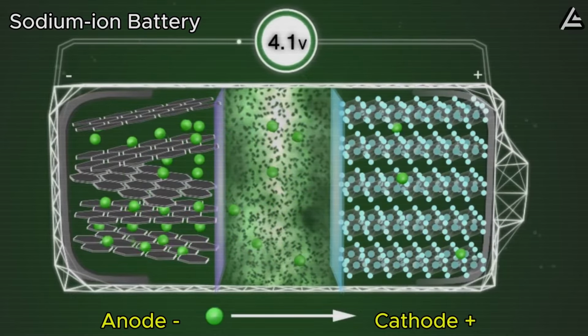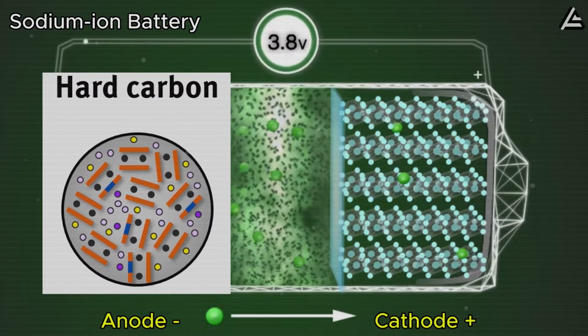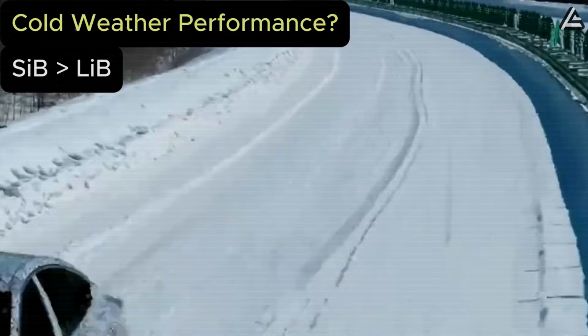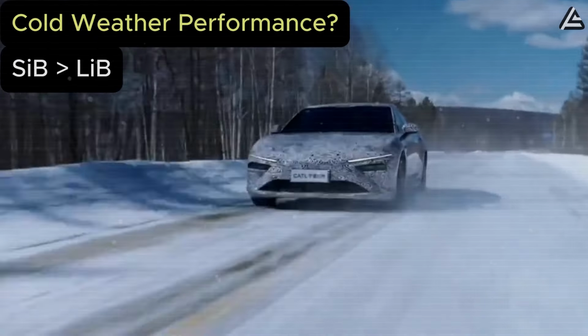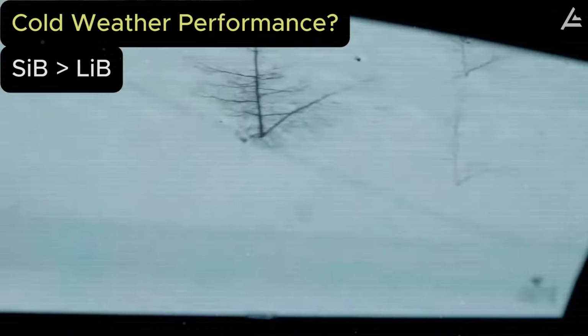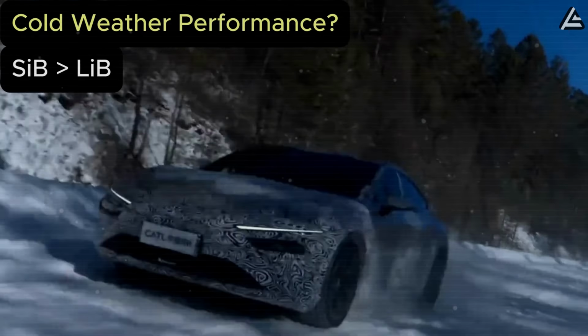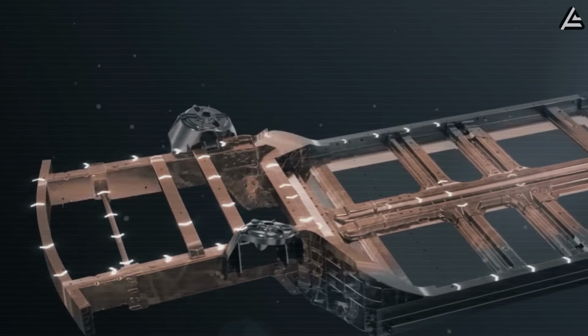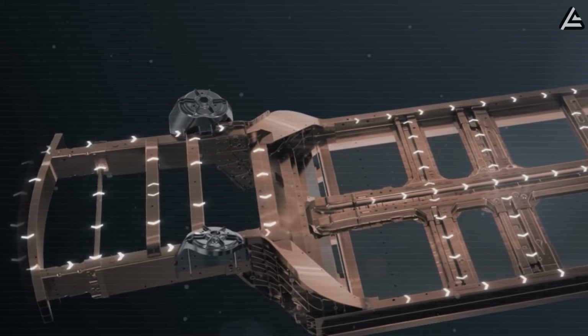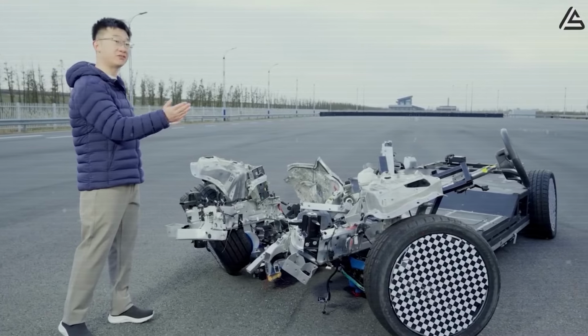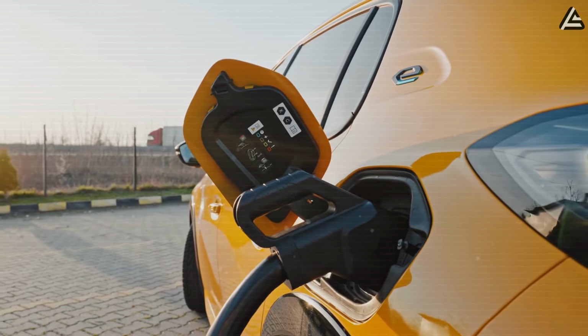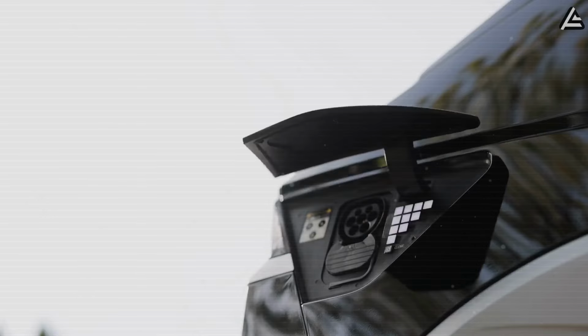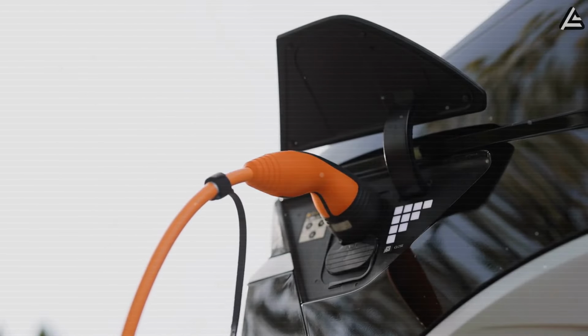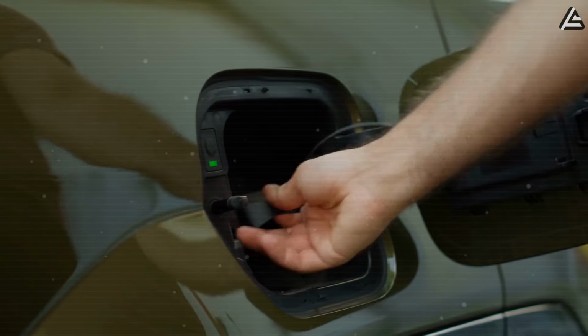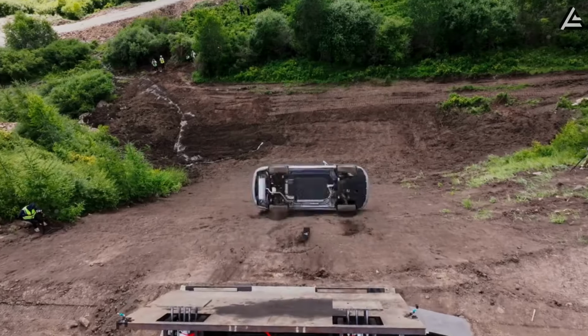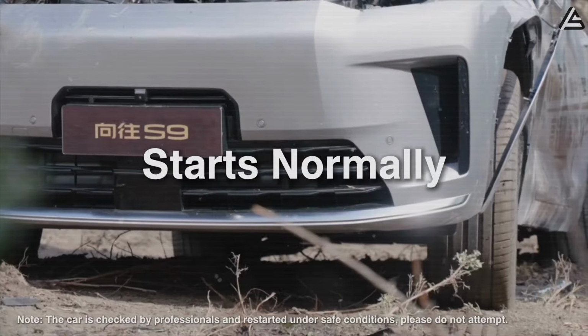Sodium's chemistry is simply less volatile. Its ions carry charge without the same eagerness to react with moisture or oxygen. Add to that its ability to keep 90 to 95% of its capacity even at minus 20 degrees Celsius, and you have a battery that feels like it was designed for Canada rather than California. The trade-off? Sodium ions are bulkier and heavier than lithium, which means slower diffusion and shorter life. Roughly 2,000 to 4,000 charge cycles compared to lithium's 5,000 plus. Overcharging can also swell electrodes, which Tesla would need to manage with precision software and cell balancing. Still, in the grand safety hierarchy, sodium ion sits comfortably near the top.